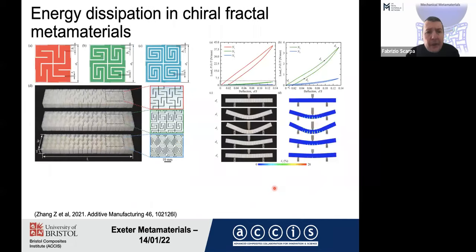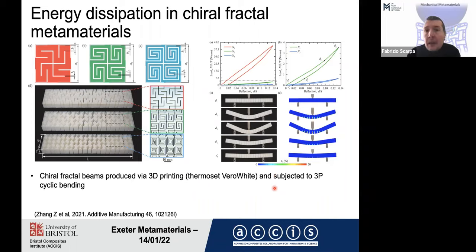We also more recently explored the energy dissipation capabilities of these chiral fractal metamaterials under bending. So we have built those samples. Those samples are actually created via 3D printing. We have used a thermoset, VeroWhite material. The bending is quasi-static but cyclic, so very low, around 0.1 Hertz.